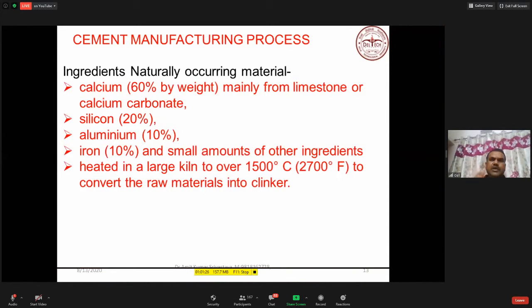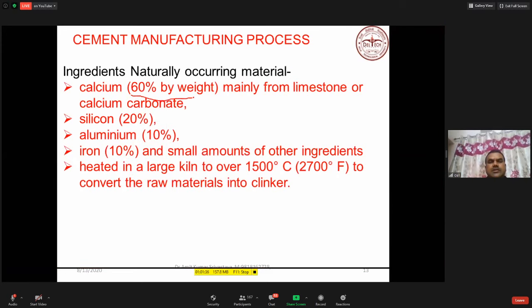If I make cement, I require raw materials which contain calcium. The calcium requirement is about 60% by weight, and this 60% we get mainly from limestone or calcium carbonate. Then 20% silica, 10% alumina, and 10% iron. These limestones are burned at very high temperature in a large kiln, at about 1500 degrees centigrade, to convert the raw materials into clinker.